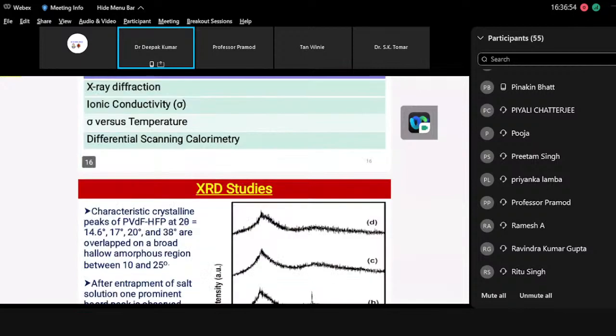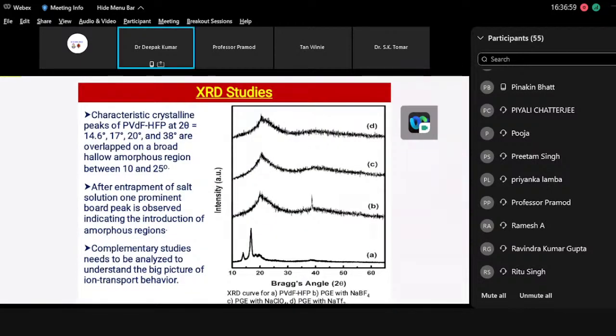So in the XRD studies, what we are observing is for the pure PVDF-HFP, the semi-crystalline peaks are observed at 14 degrees, 17, 20, and 38. And these peaks are basically overlapped on a hollow amorphous region, which is observed from 10 to 25 degrees. Once we incorporate the salt solution, I mean the sodium salt immobilized in the TEGDME, then we observe the peaks are reduced, but there is some indication of the salt. Smaller peaks are observable. So to further analyze, complementary studies are required to understand the big picture of the ion transport which is happening.